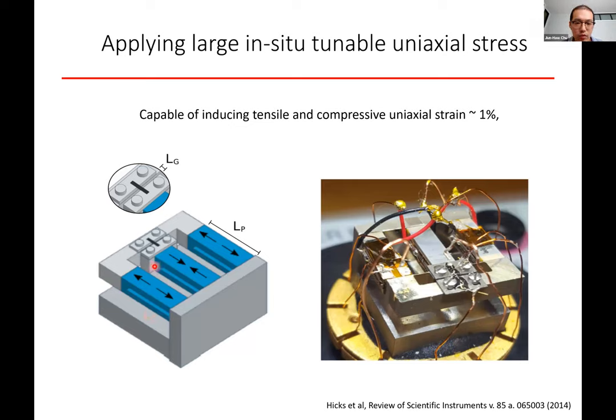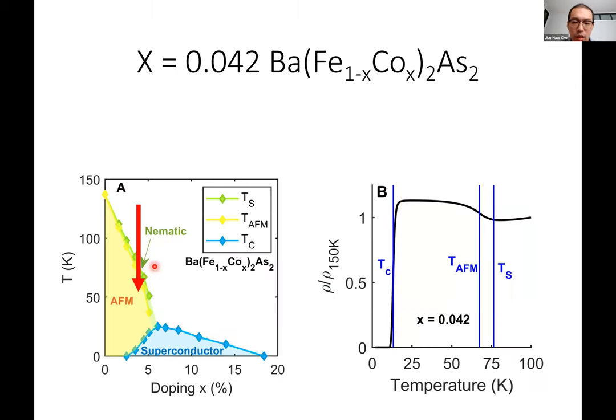So this is a really useful device and technique to study quantum materials. Let me start with a material that already has a nematic phase and an antiferromagnetic phase, a composition around this part of the phase diagram. On the right is the resistance versus temperature of this material. As you cool down, first you see an upturn corresponding to the structural transition, then an inflection point corresponding to the antiferromagnetic transition temperature, and finally a drop at a Tc around 13 Kelvin.